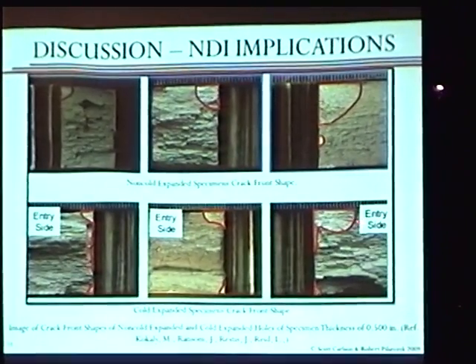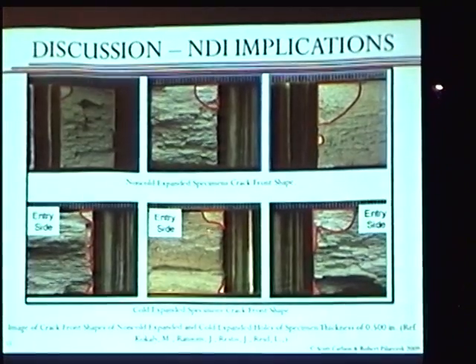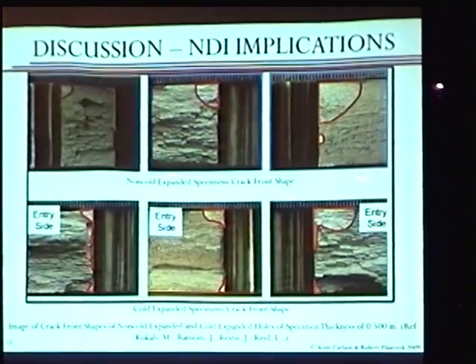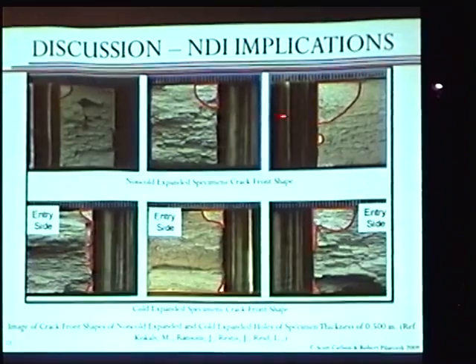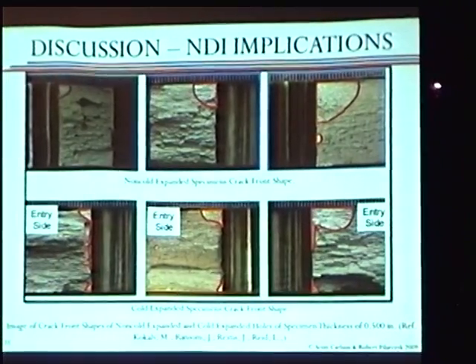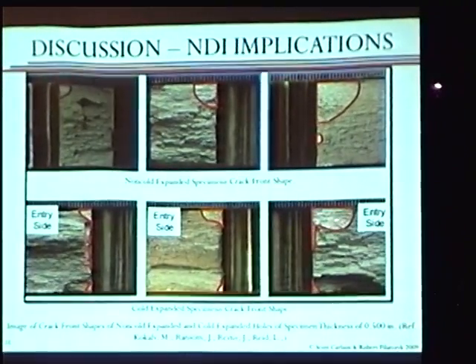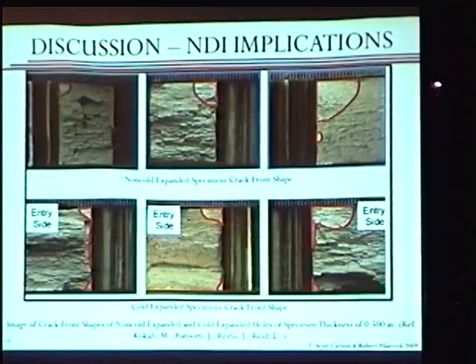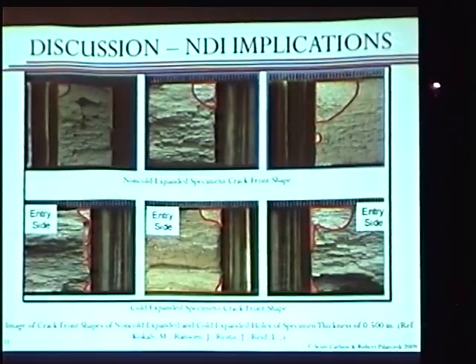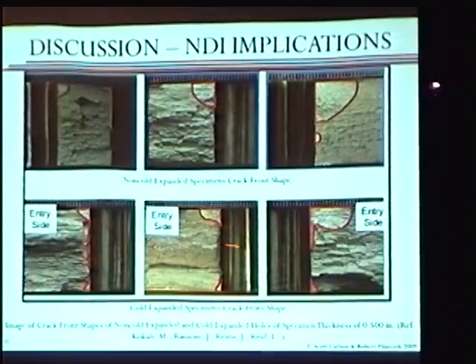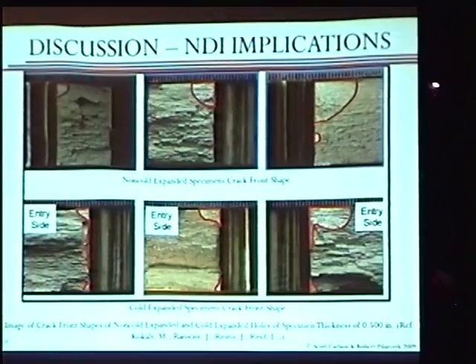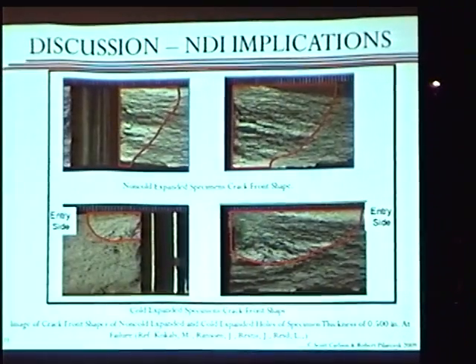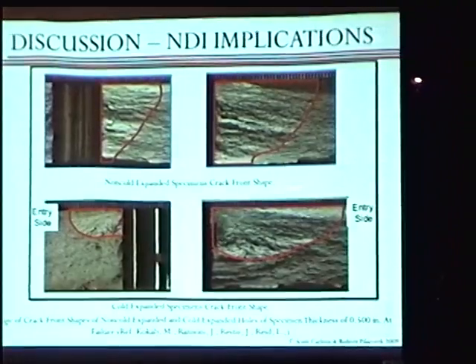really explicit type of P shape and some really unique crack fronts. But what you see, these are non-cold work specimens, nice, neat corner cracks that you see in the components. You've got these just really odd crack shapes that you really need to think about, get in your mind when we start thinking about what type of NDI inspections we want to do. Next slide. So this is also half-inch non-cold work specimens.